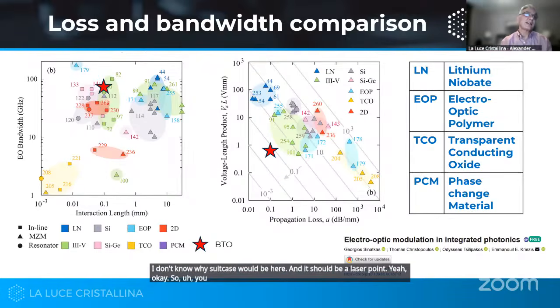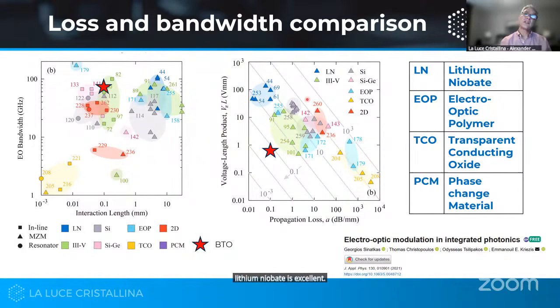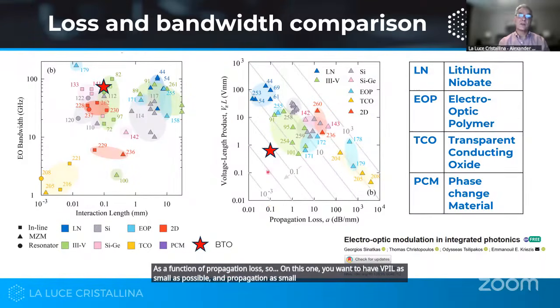Yeah, okay. So you can see that barium titanate is actually pretty good. Lithium niobate is excellent, of course. And then this is the V-pi L, right? So it's somewhat device dependent, but that's efficiency of modulation as a function of propagation loss. So on this one, you want to have V-pi L as small as possible and propagation loss as small as possible. So you'd like to be in this empty corner.